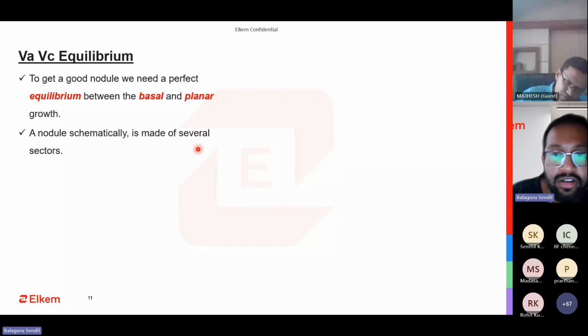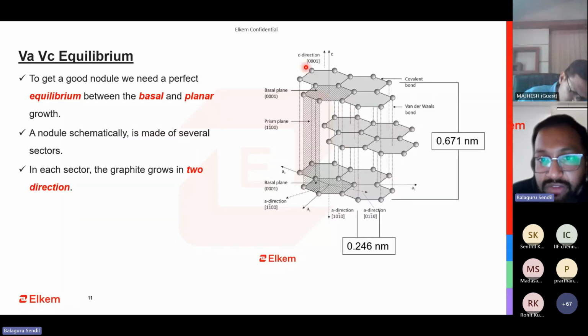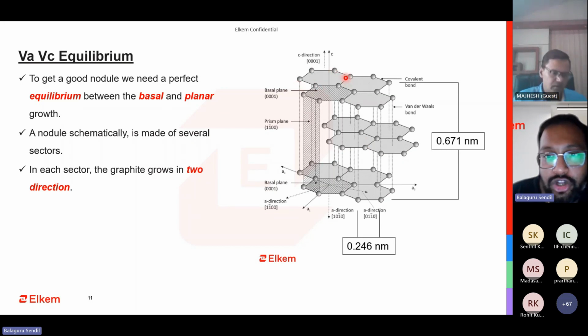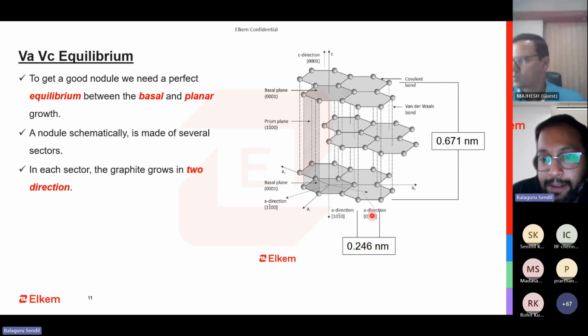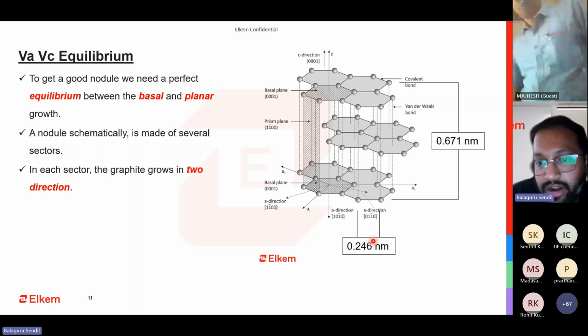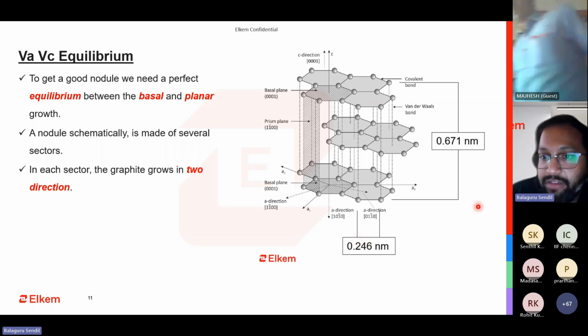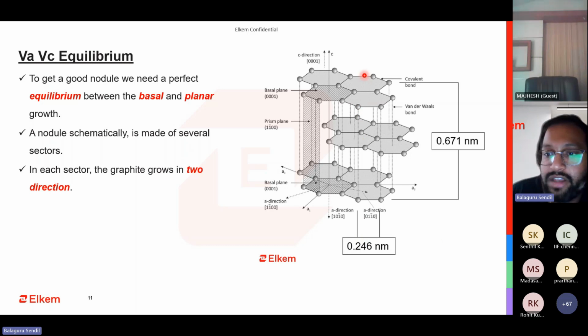Again, we discussed here, this is the structure that we showed in the first couple of slides. If you look at it, this is the hexagonal structure of the carbon. This is growing in the A direction, and this is the basal direction, and this is the planar direction. If you look at the distance between these two, it is about 0.671 nanometer, and this is about 0.246. If this 0.246 keeps going at a faster rate, you get a flake. If this keeps growing at a faster rate, you get a nodule.